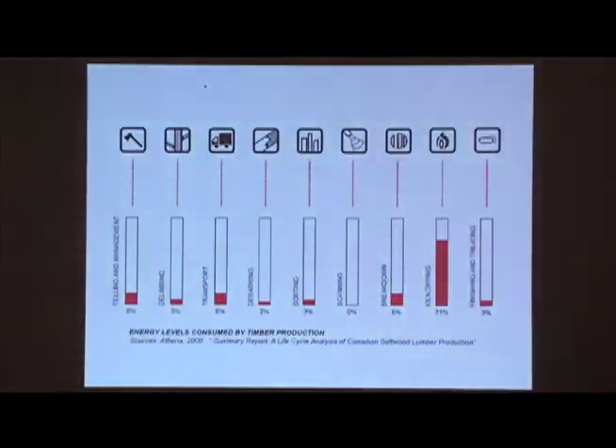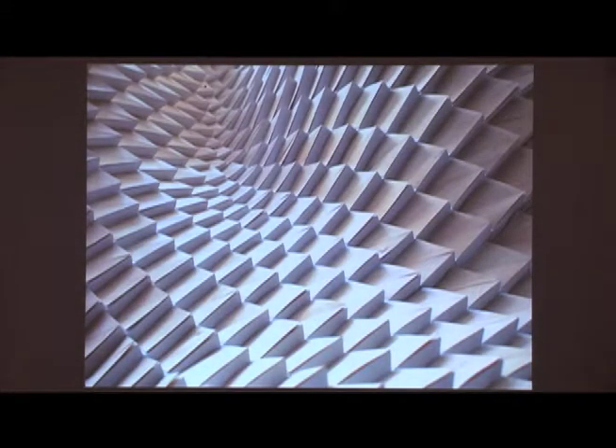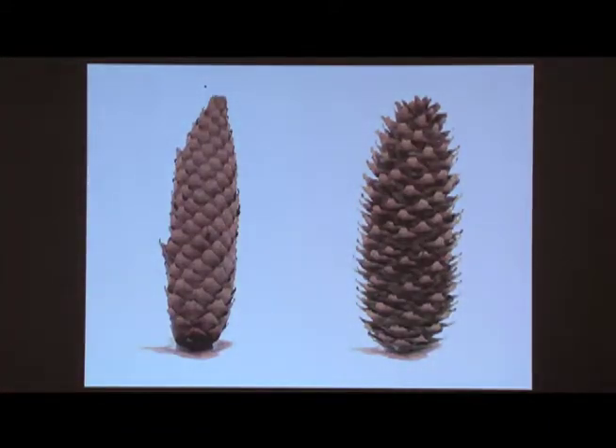So we thought, how can we utilize that behavior, which we usually try to get rid of? Within an otherwise low-energy process, we spend 70% of the energy in wood processing just to make sure that wood does not respond to changes in relative humidity. So we thought, if we leave that kiln drying out, what can we do with this behavior? Obviously we can utilize the hygroscopic dimensional change to trigger a shape change, and that could, for example, allow us to construct an environmentally responsive surface structure that adapts to increases in relative humidity by ventilating, automated ventilation. A system that we know does exactly that is the spruce cone.